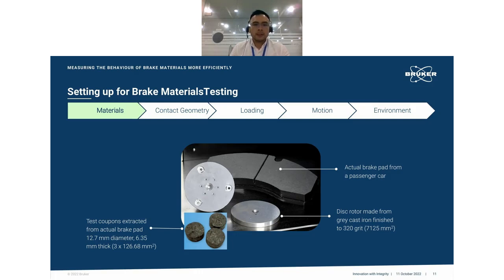So typically, to set up an evaluation test to determine tribological properties of friction materials, you need to first define the five most important tribological elements, which are the material, contact geometry, loading, motion, and environment. So for our case,